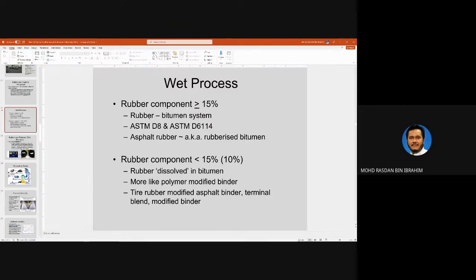So it is more towards a rubber bitumen system, meaning to say here, it is not stable actually. If it's more than 15%, to get a mix that is stable, a terminal blend, is quite impossible. But when it is less than 15%, typically 10%, rubber can be dissolved in bitumen and it can perform like other types of polymer modified binder. Okay, so this is quite new. It is still under much research, the terminal blend of rubberized bitumen.